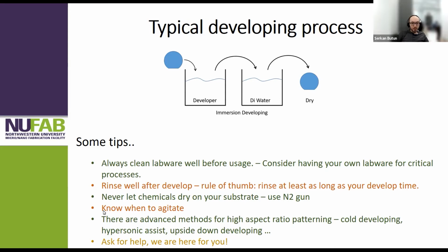And the other one I see a lot in the lab is that sometimes people just leave their substrates on the bench when the chemicals are on it still. That's usually a really bad idea, because due to surface tension, or sometimes the surface of your wafer is not very hydrophilic, the water or solvent, whatever is on it, will start to run, and it will start drying from the edge. And as soon as it dries, it deposits whatever contaminants are in there on your substrate, and they will get very hard to clean later. So you should always use a nitrogen gun after your work is done. All right. So that is your most important job.